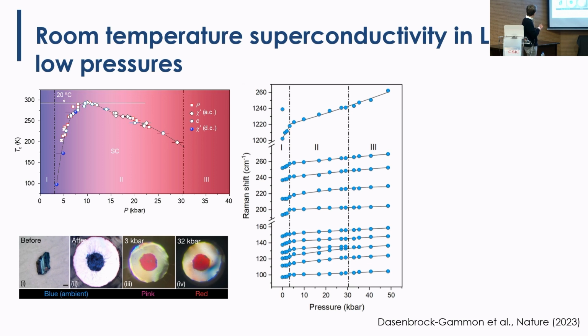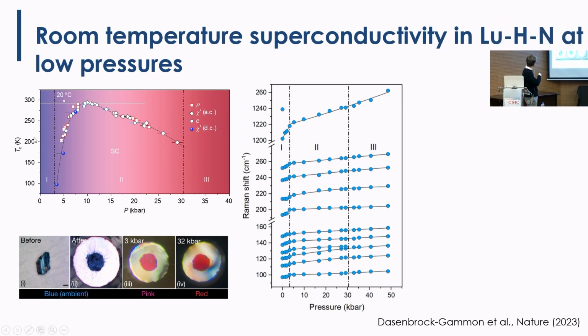Okay, where is the color change here? Okay. So basically, they started measuring superconductivity with a critical temperature of around 100 Kelvin, at, this is not gigapascal, this is kilobars, so it's 10 times less, okay? So 10 kilobars is 1 GPa. So this is nothing, this is 1 GPa. And the critical temperature was increasing a lot in a very narrow pressure range. So this is very anomalous with respect to H3S, lanthanum H10, and the others. The others have, over 100 GPa, pretty much a constant critical temperature, with a very small oscillation. This is very different in that sense.